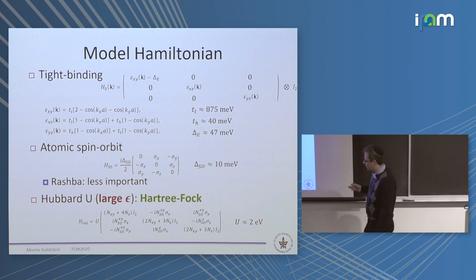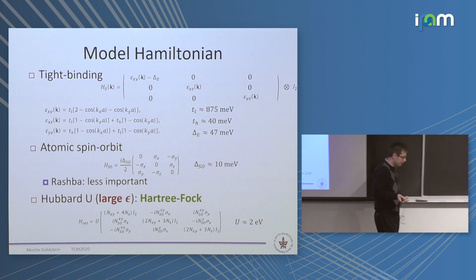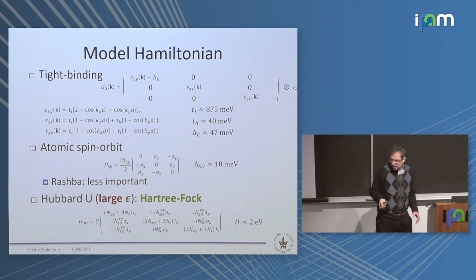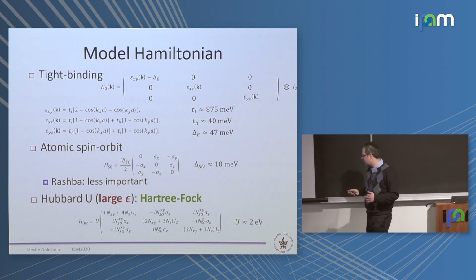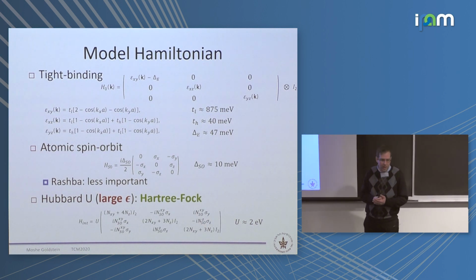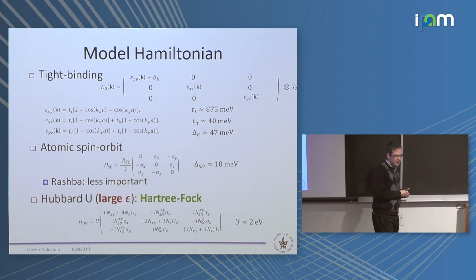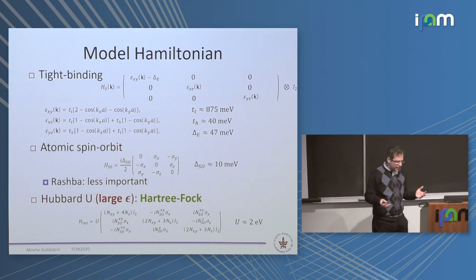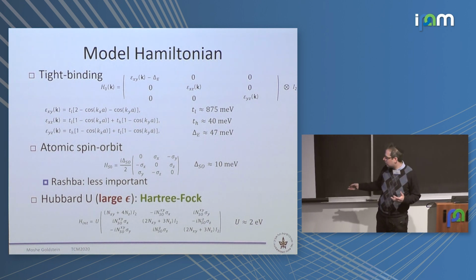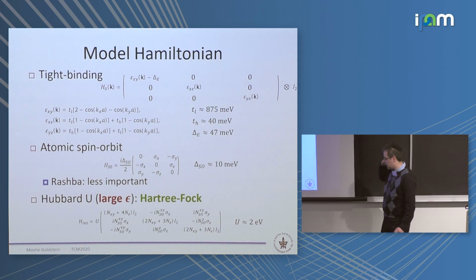And then we need to take into account interactions. Our model for interaction is going to be a local Hubbard U. The justification for that is that because we have such a high dielectric constant in the STO, 20,000, the long-range part of the Coulomb is going to be much suppressed by this dielectric constant. So it's not going to play an important role, at least not for the effect I'm discussing. So the short-range part is the important thing.